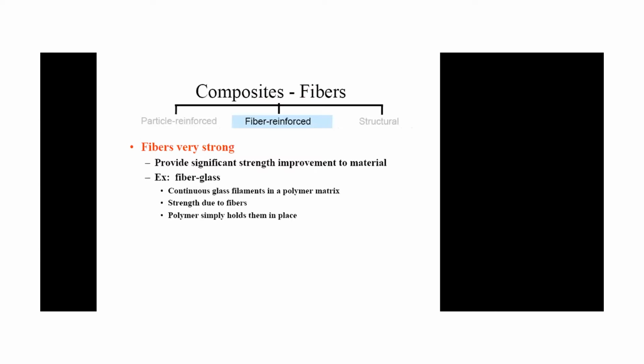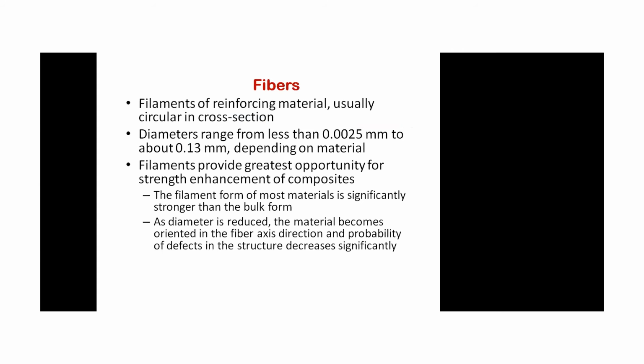In case of fiber reinforcement, we are adding fibers. Actually, fibers are very strong as compared to bulk material. If you make a fiber of any material and compare it with the bulk property of that same material, it gives you higher properties in that direction only, not in the transverse direction. So we are using fiber reinforcement, like fiberglass. We're adding glass filament to polymer, and we get strength because of the fiber, and its strength increases. The fiber is basically the reinforcement material.